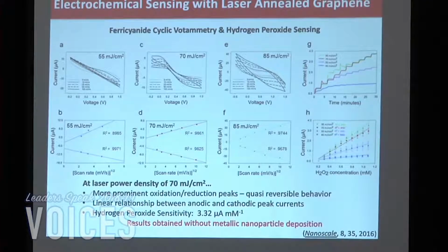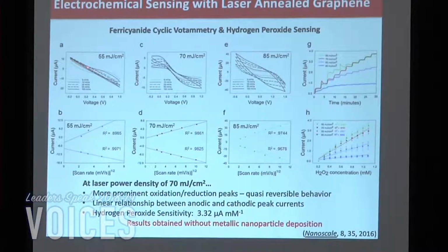And all of this is done, of course, on a flexible electrode, but that patterning of the surface can make the surface electrochemically active as well. So we have all that surface area. It's good for catalysis, and these are just cyclic voltammetries in an electrolyte, a ferrocyanide probe. And we just get shapes that we'd expect for a platinum wire that was in a vial as well. So it's behaving potentially as a good sensor, and we're doing hydrogen peroxide sensing here at different concentrations. And all we're showing in these graphs is that at lower lasers, we don't really see the oxidation peaks or the redox peaks that you'd expect from an electrochemical sensor, but when we ramp up that laser, it starts becoming the bird-like peaks that we'd expect from redox reactions. So it's becoming more electrocatalytic and a sensor that is useful for biosensing.